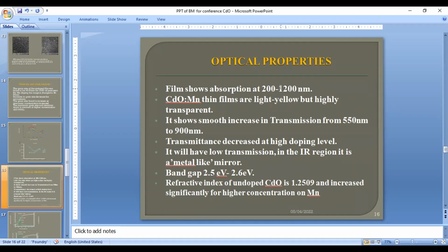The transmittance decreased at high doping level. I already told that 0.02 is giving the good transmission, but if we increase the doping to 0.03, it also decreases the transmittance nature. That's why we can give the range from 200 to 1200 nanometers. It will have low transmission in the IR region. It's like a metal-like structure, a mirror, the reflecting nature.